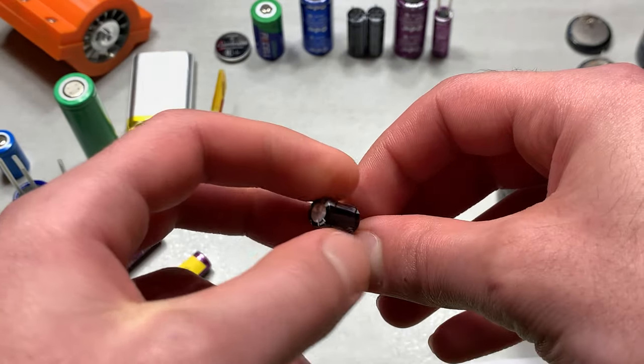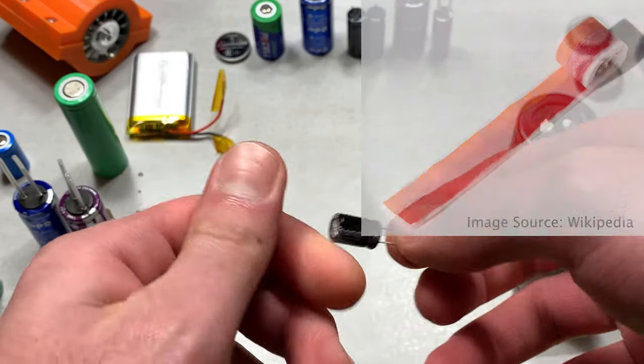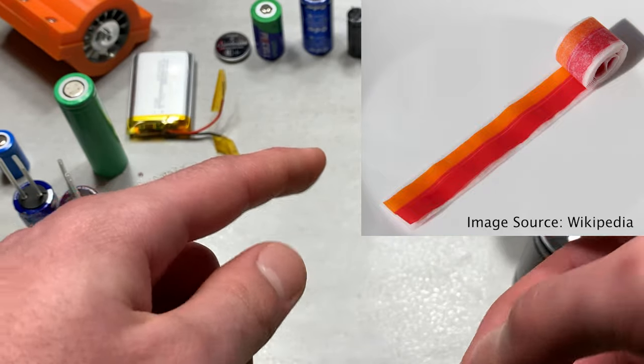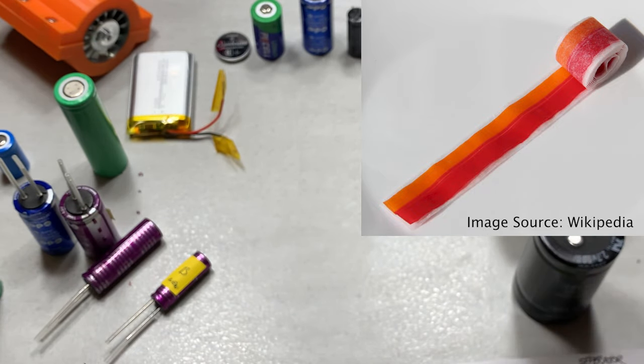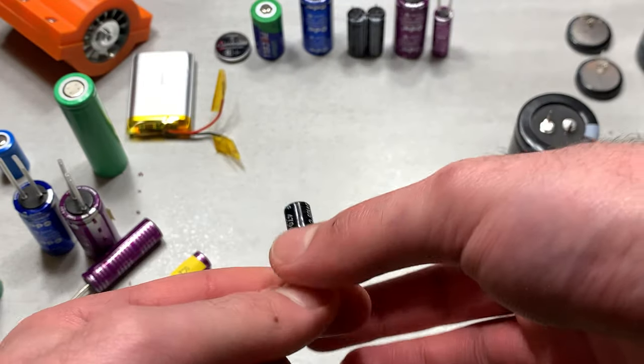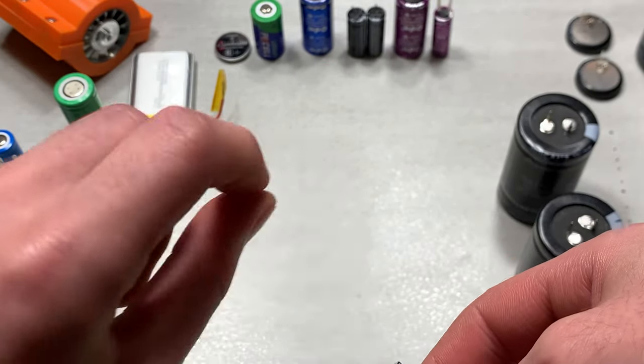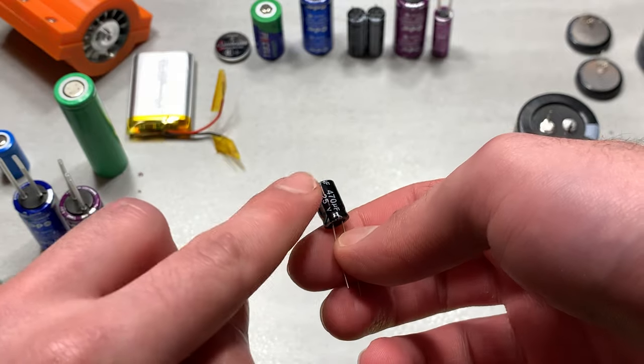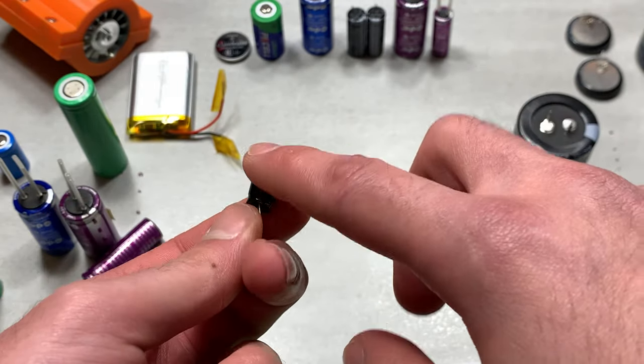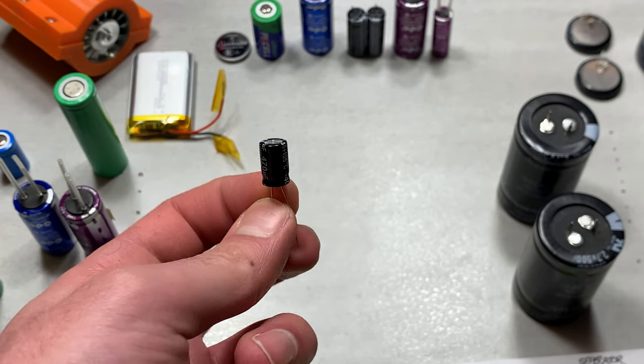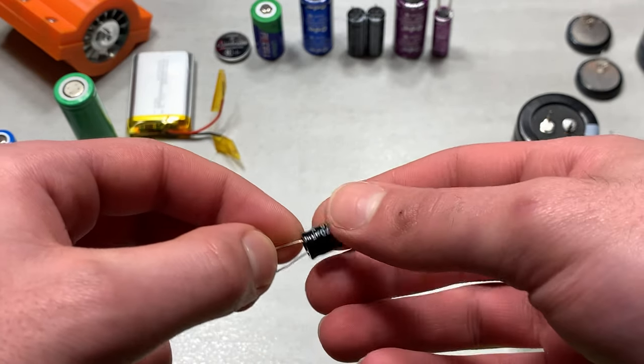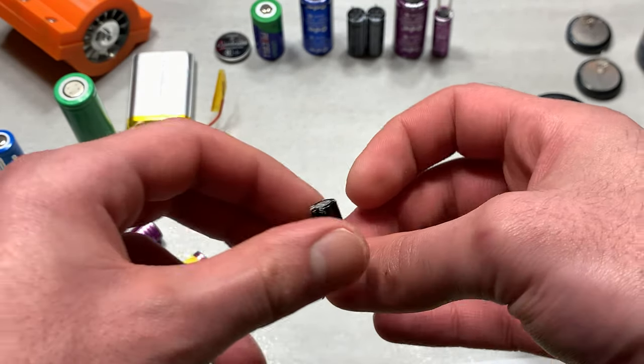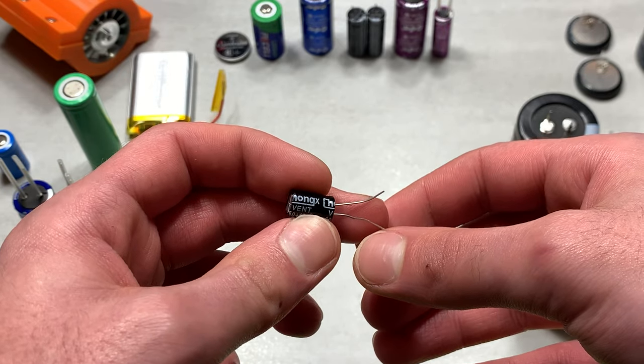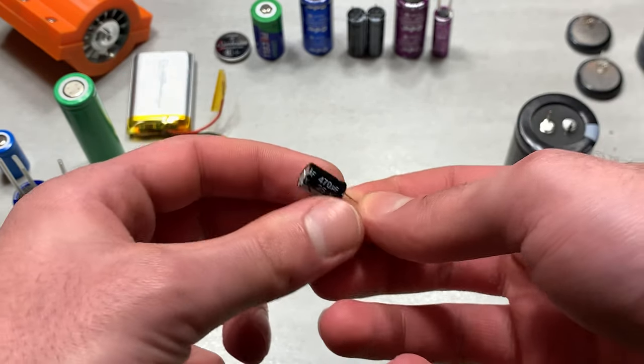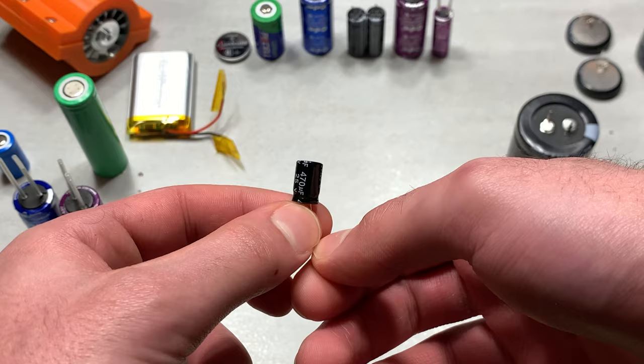Basically, the inside of a capacitor is sort of like one of those fruit by the foot rolls, where you have a very, very long piece of separator with your two electrodes, and typically the separator is soaked in the electrolyte. And then you have your two aluminum electrodes, in the case of the electrolytic capacitor, on either side, which are then connected to the respective leads and encapsulated in this package, designed to vent in a specific direction should there be a catastrophic failure.